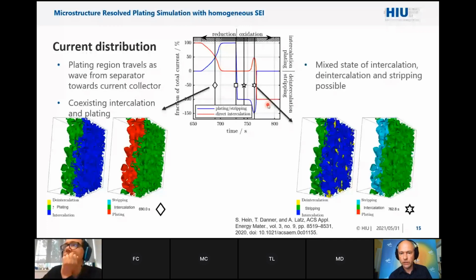So here we are now in that situation, and what you see here is very amazing. You have a plated film, you turn around the current, you strip your plated film. Eventually, all the lithium is resolved. So all the lithium is again in solution. But what you see is that you get a very inhomogeneous picture. You don't have only stripping. You also have parts where you have full intercalation, and only here you have de-intercalation.